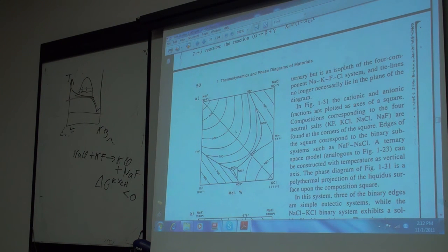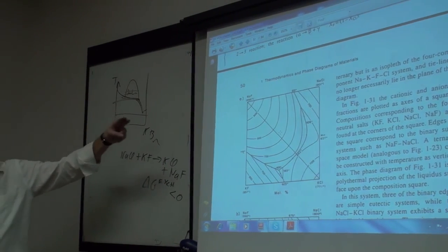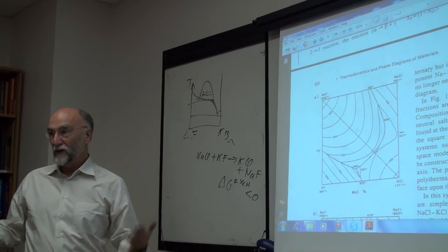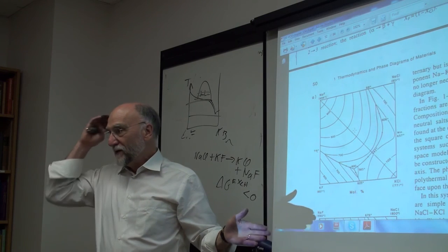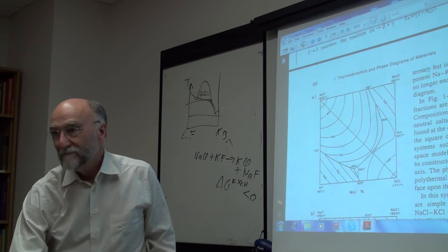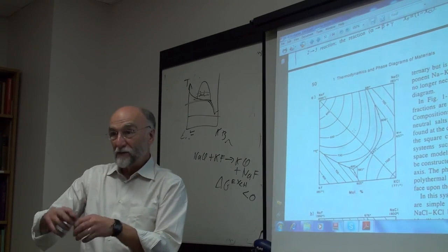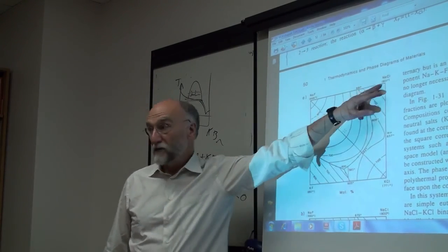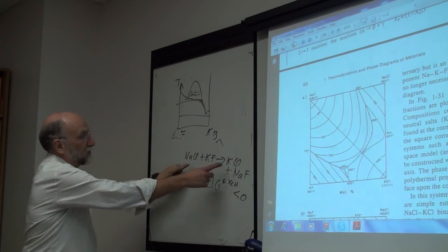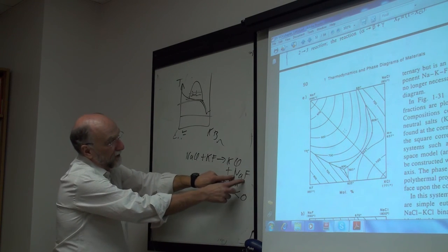Okay, this is the stable diagonal. This actually seems paradoxical, backwards. If NaF and KCl are the stable pair, if delta G is negative, then you think along the stable pair you might expect to get negative deviation. Stability, negative deviation. But along the stable pair, that's where you get positive deviation. They don't want to mix. Potassium likes to stay next to chlorine, first nearest neighbors. KCl and NaF nearest neighbor bonds are preferred over KF and NaCl nearest neighbor bonds. Okay, when you mix NaCl and KF, you're forming strong bonds. You're forming KCl and NaF.